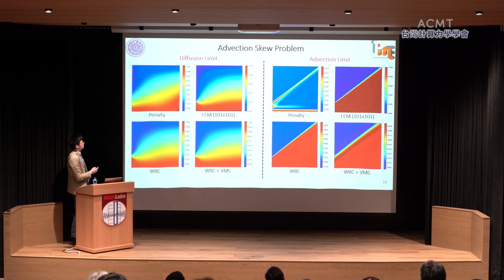And this is the famous advection skew problem. You will see that in the diffusion limit, even the penalty method, where I didn't choose the penalty but already regularized it, does not satisfy the boundary condition very well. The two proposed schemes match the FEM solution. For FEM I use 100 by 100, and for this one I only use 10 by 10 neural network sampling points. You can see the accuracy is amazing.